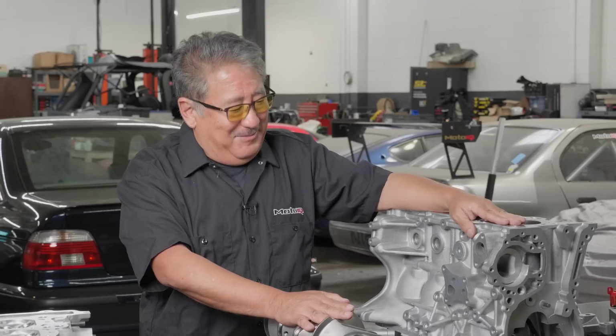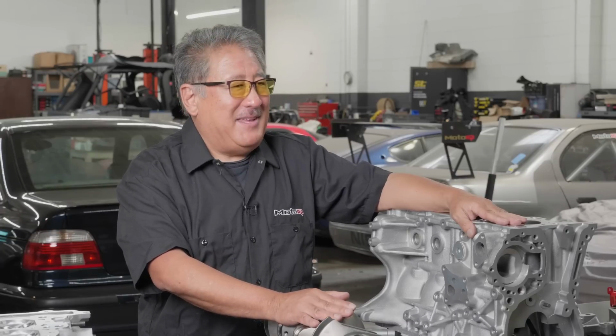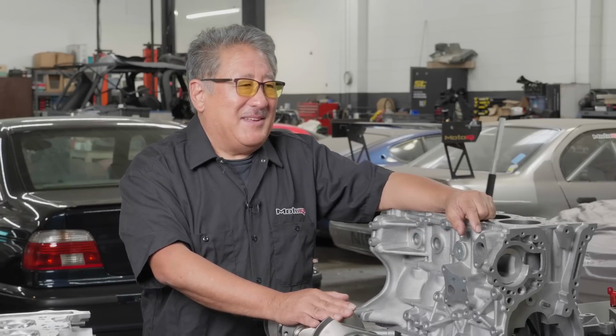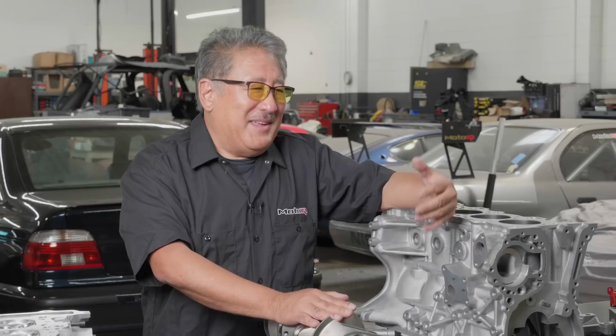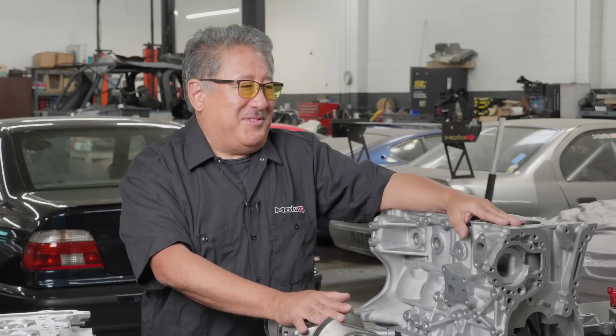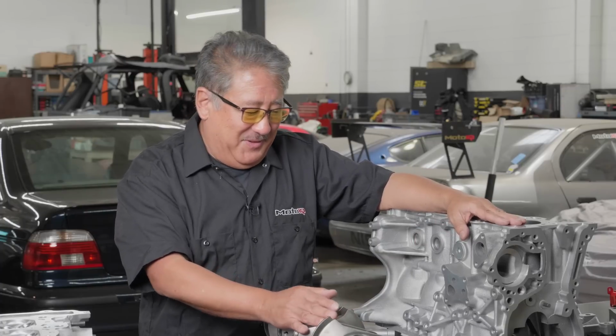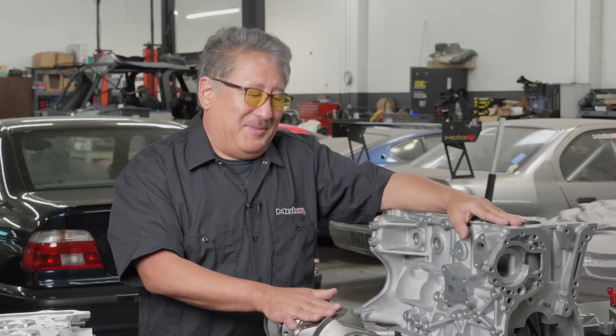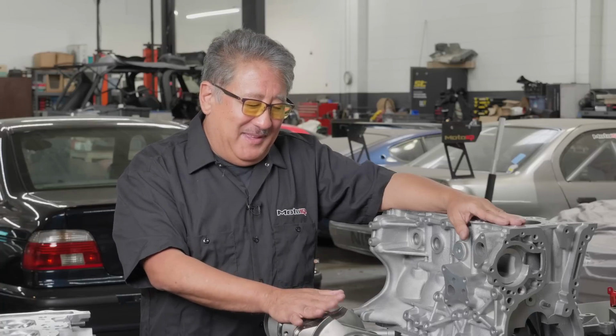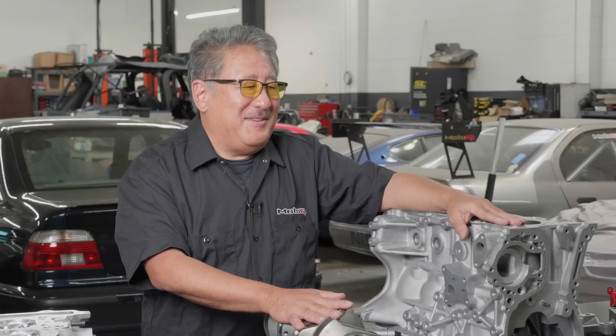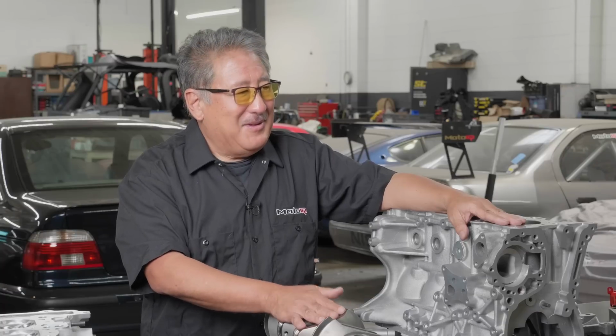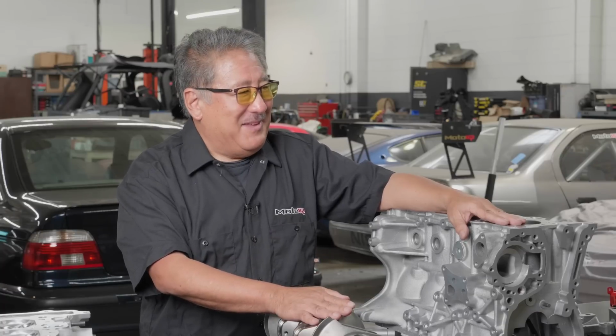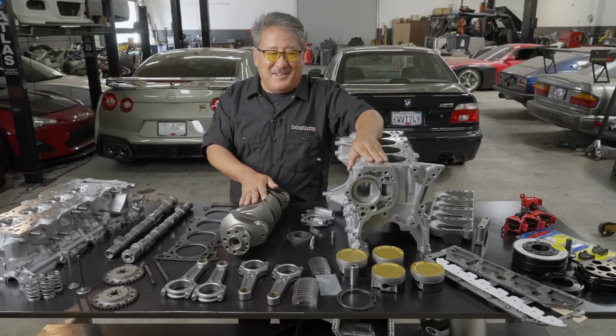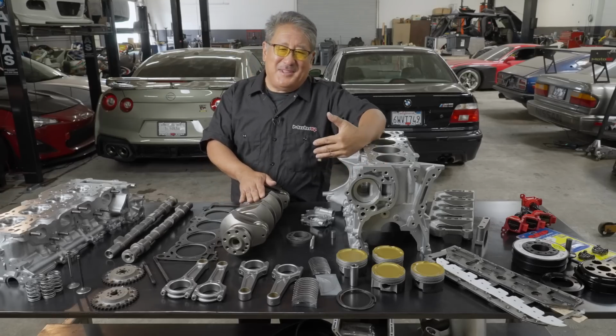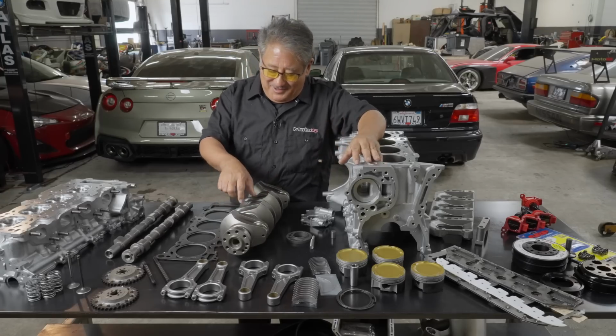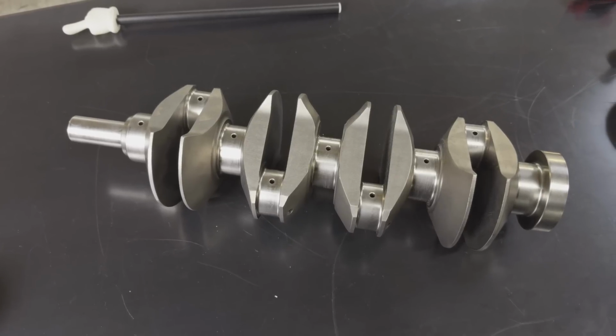maybe 8/10 or something into the surface, but shot peening with the bigger media can actually refine the grain and everything maybe as much as 3/1000 into the part. So shot peening really helps fatigue strength and everything, and it's a good process with basically free strength. Even though this crank is stroked, SR20 cranks are pretty beefy and they have a lot of journal overlap, which lends to stiffness.